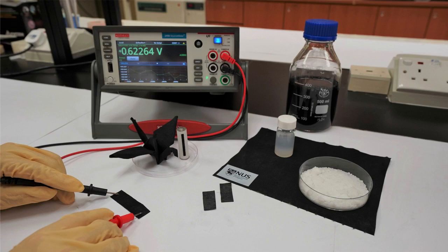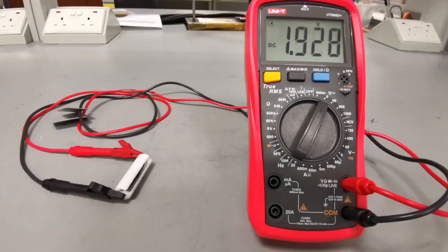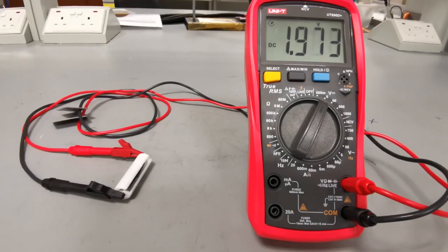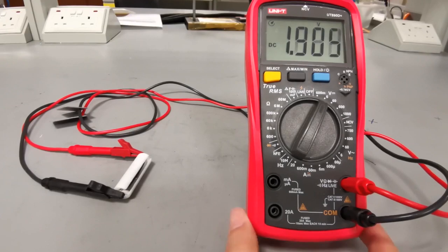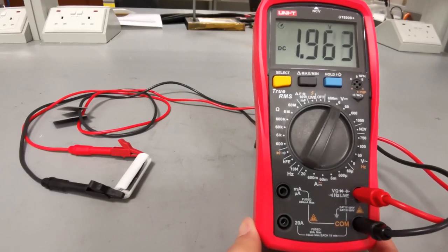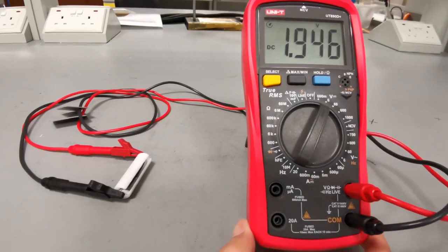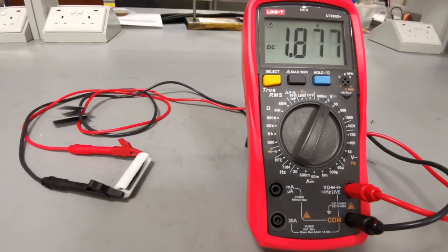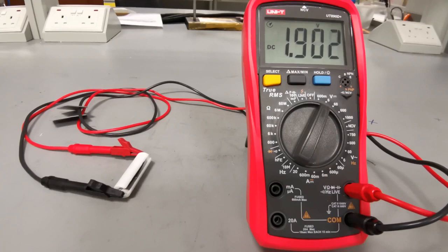The NUS team has also successfully demonstrated the scalability of its new device in generating electricity for different applications. The NUS team connected three pieces of the power generating fabric together and placed them into a 3D-printed case that was the size of a standard AA battery. The voltage of the assembled device was tested to reach as high as 1.96 volts, higher than a commercial AA battery of about 1.5 volts, which is enough to power small electronic devices such as an alarm clock.